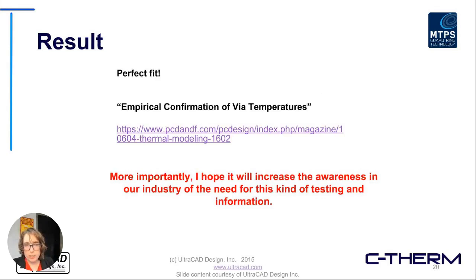And the end result of that is actually something that was published in Printed Circuit Design and Fab that you can see in this URL here. So that provided the confirmation for his initial simulations that he felt would verify the fact that the via temperature is dictated by the trace temperature and the trace current, not necessarily by how much current is actually passing through the via itself. So the consequence of that is that you might need quite a bit fewer vias than would be dictated according to these initial guidance documents that don't take into account the cooling provided by the board itself.